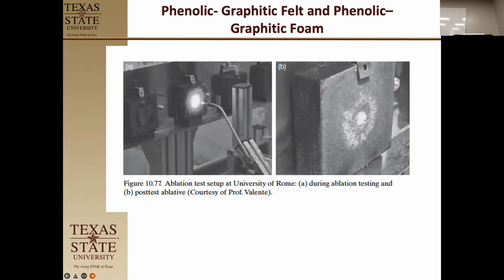Okay, so this is different. This is not like the rocket motor test. This is the oxy-ablation, I'm sorry, this is the acetylene torch ablation test. So it's the OTB, oxyacetylene test bed. And it has a fixture that holds this here, and then you have a timer. And again, it's clamped down your sample here, and it's going orthogonal to the system. Gases are washing across it, that kind of thing. And so what you see here is in the center is where you get the highest amount of ablation, but then there's a ring of where it's high heat flux, and also stuff that's been moved off. And then by the time you get out here, most of the heat and or gases have dissipated, so there's less damage. So you'll see that kind of pattern in the system.